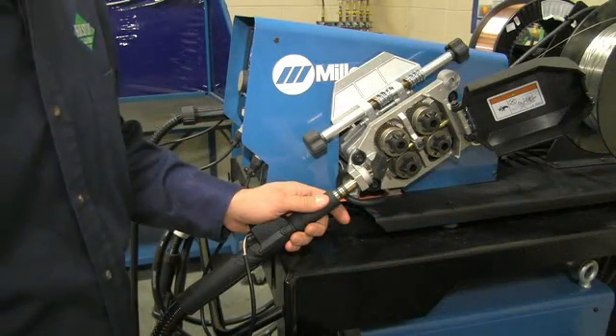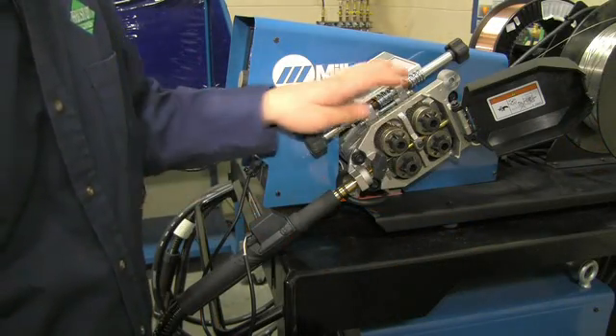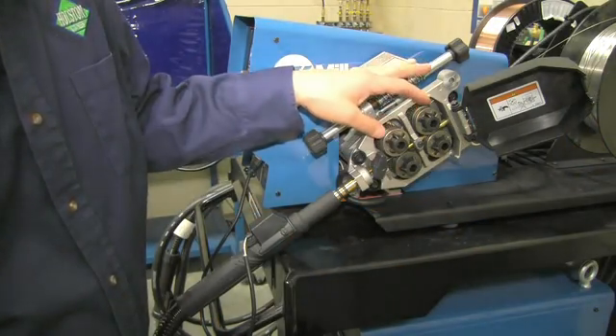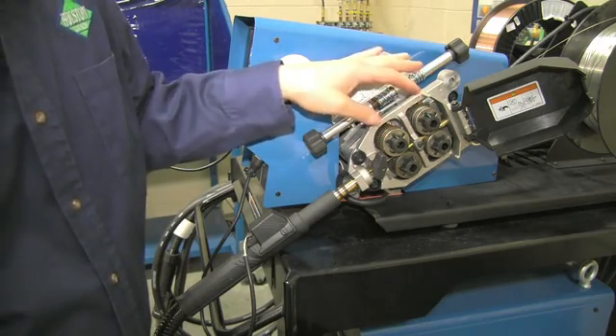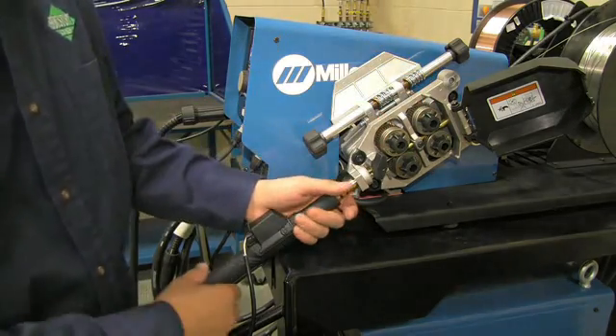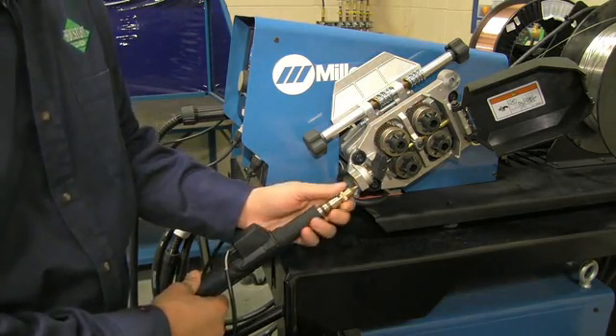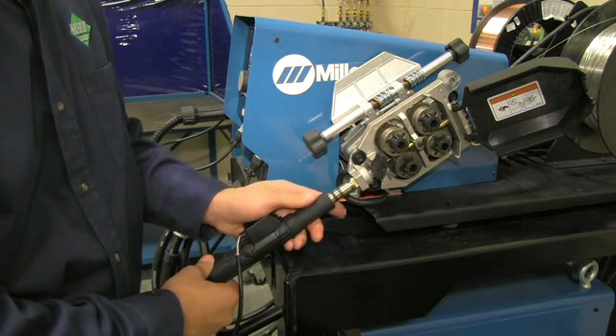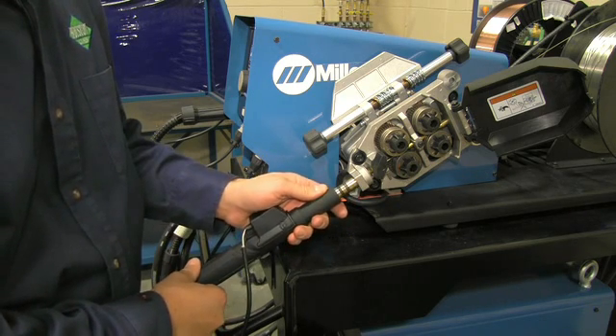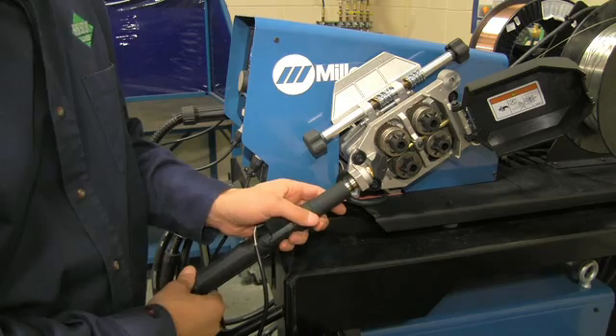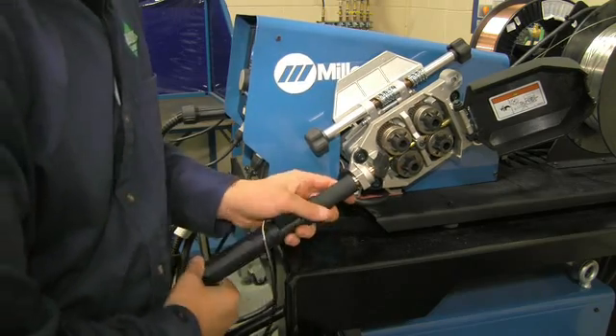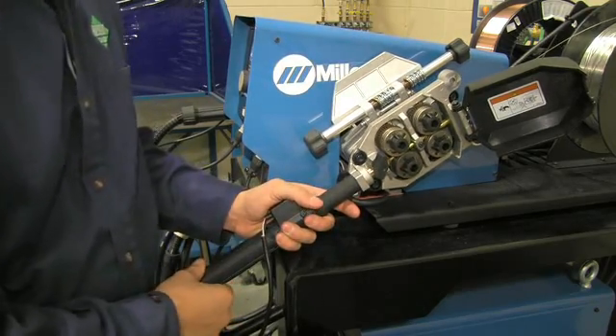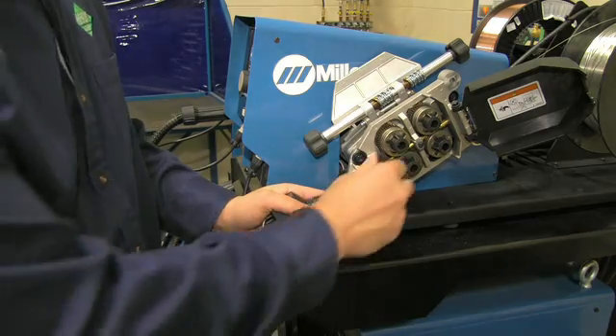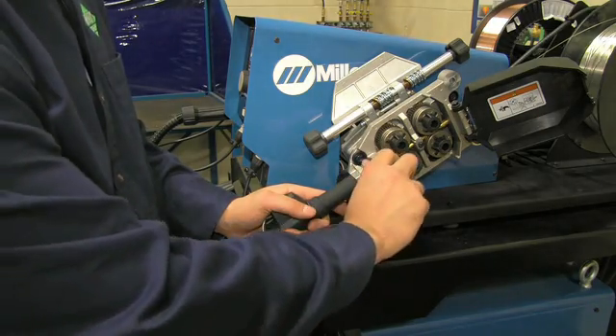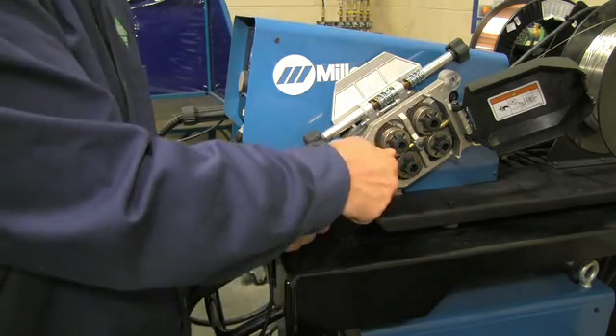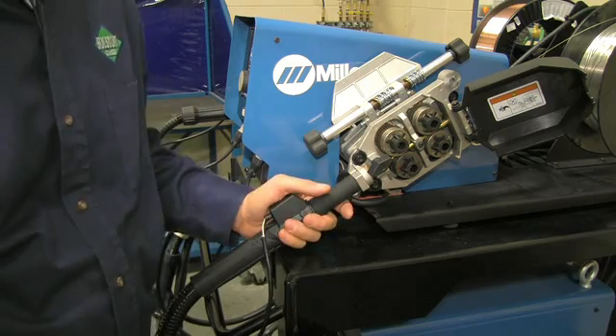So here we have a benchtop feeder, and this is the wire drive housing of the feeder that houses the drive rolls and the gears that push the wire through the system. And here is just a simple MIG gun with a power pin. Typically when you get a new system, you push the power pin into the wire drive housing and seat it all the way as far as it'll go. Then the proper thing to do is to tighten this nut down, as hand tight as you can get it, and you should have a sound system.